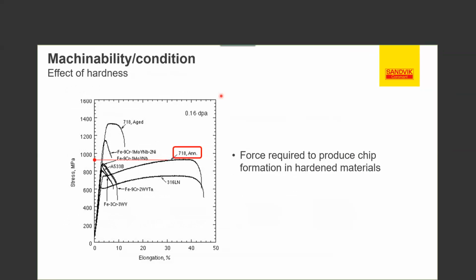For instance, if you take a piece of 718 that's annealed, basically the stress to create a chip is going to be about 900 megapascals. Whereas if you have something that's aged hardened, 718, same material, just different treatments, you're going to be upwards of about 1350 megapascals. That's about a 40% increase. So what does that mean? You're going to have to approach this material slightly differently: different techniques, different grades, different types of geometries.